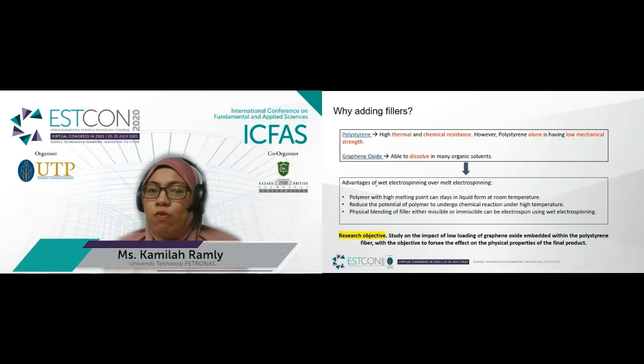The advantage of wet electrospinning over melt electrospinning is that polymer with a high melting point can stay in liquid form at room temperature. It can reduce the potential of the polymer to undergo chemical reaction when applied under high temperature, and physical blending of filler, either miscible or immiscible, can be electrospun using wet electrospinning. Hence, the objective of the research is to study the impact of low loading of graphene oxide embedded within the polystyrene fiber.